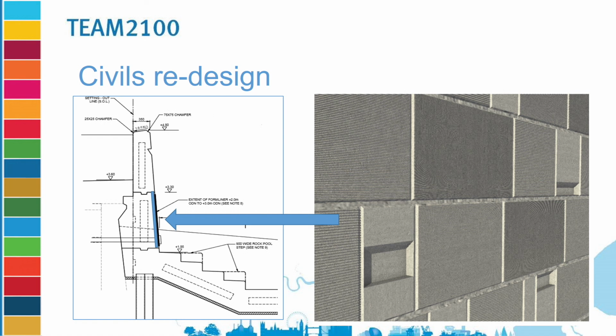So we're looking at different techniques that we can use to add additional texture to that concrete at quite a depth, probably around 60 to 80 millimetres, in order to give that concrete an ability to trap and hold some form of biotic activity, so we generate niches. Interestingly, not only does doing this generate that biological outcome, but it also makes the concrete more resilient to the drying and wetting process and the thermal characteristics of it. So it means that we end up with a longer asset life for that same asset. So actually we're winning in two ways here, if you like. So that was a final thing.